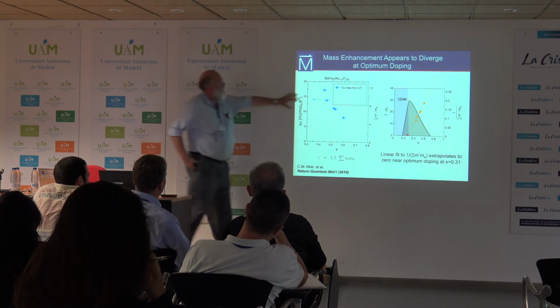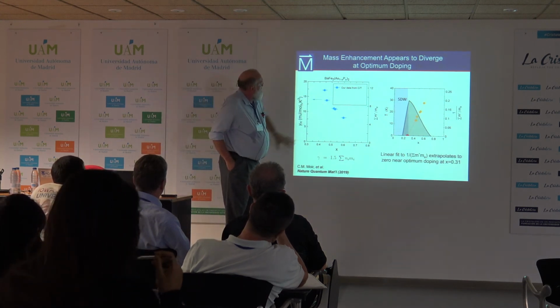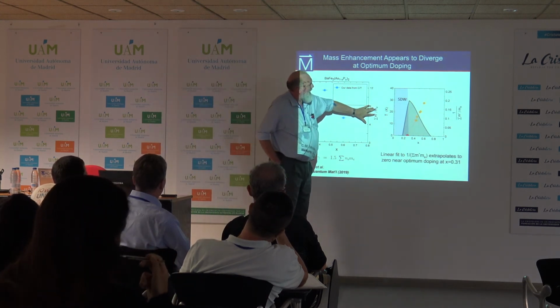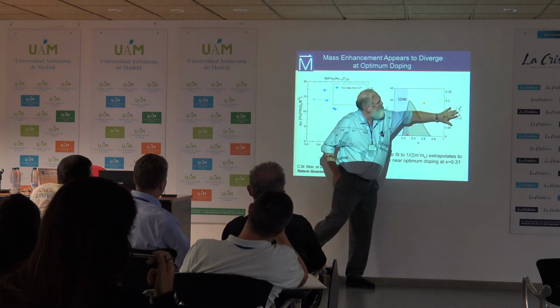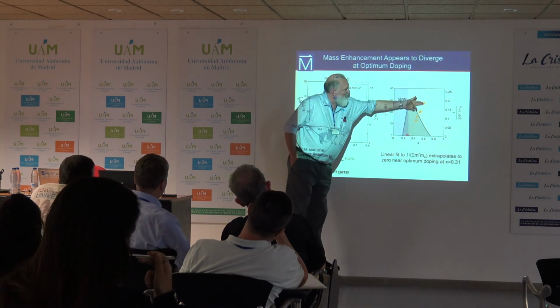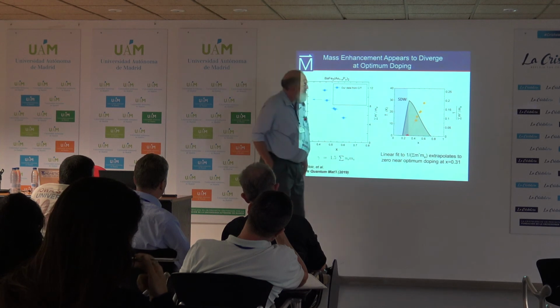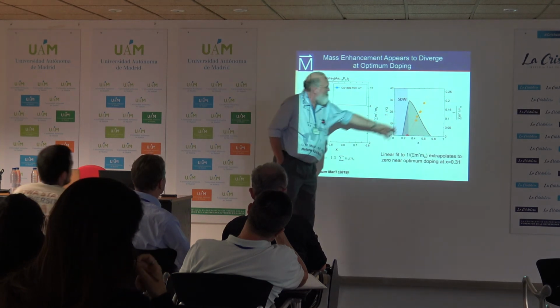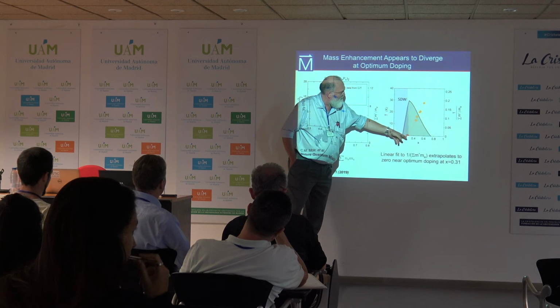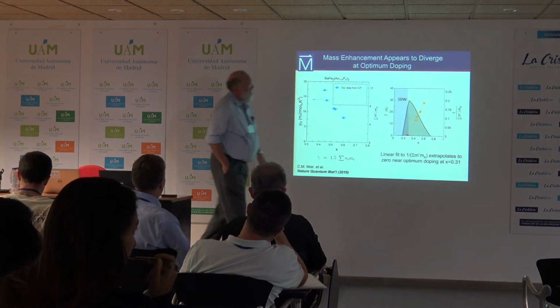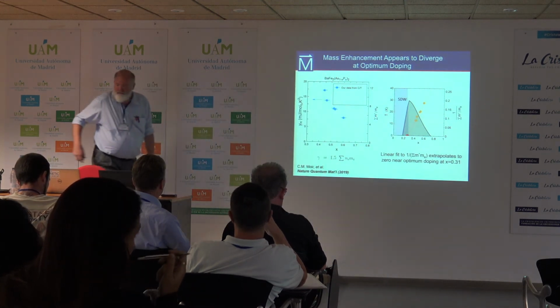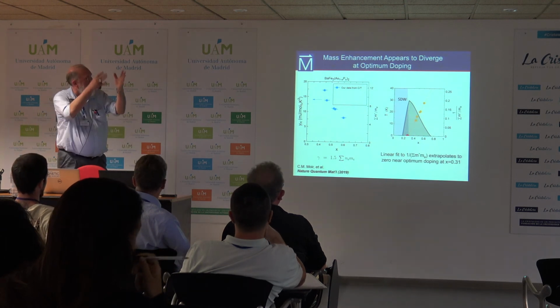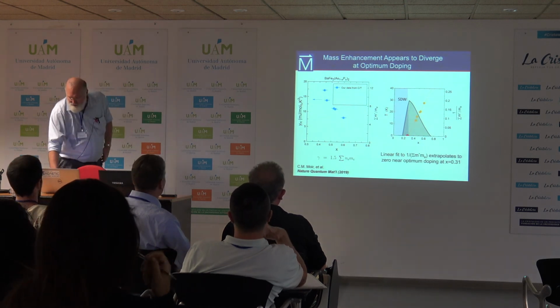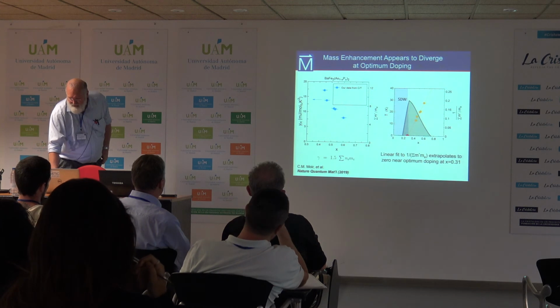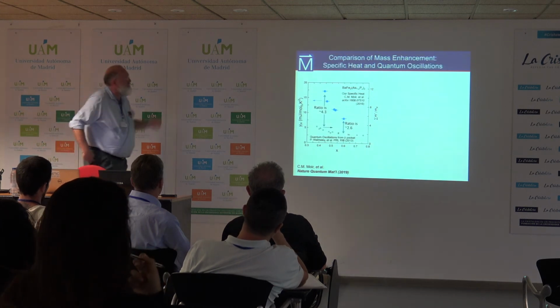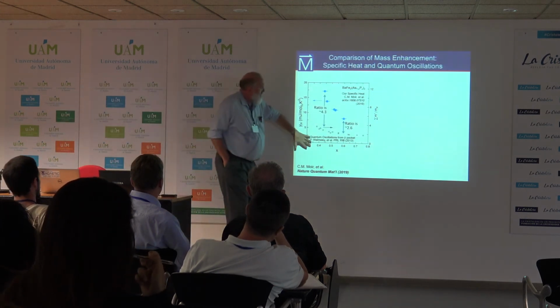So if we take these data now, and instead of plotting in terms of mass, we plot as 1 over the sum of the masses, then the data, once again, much like Brad Ramshaw's quantum oscillation data in YBCO, seem to evidence a divergence of mass right at the optimum doping. So this mass divergence, the idea is that right at that phase transition at optimum doping, you've got a mass divergence.